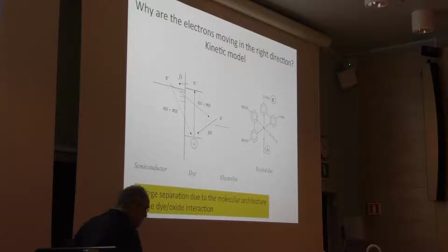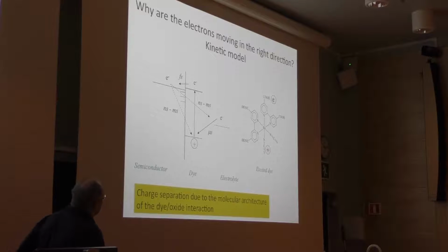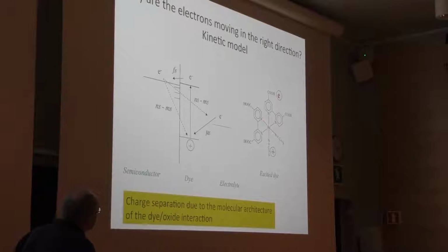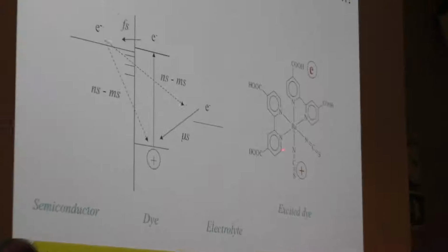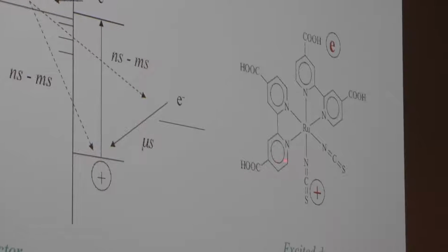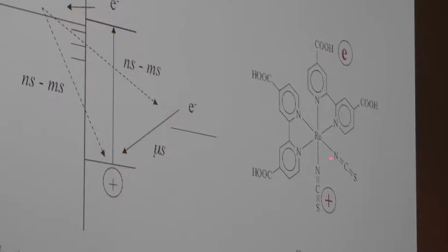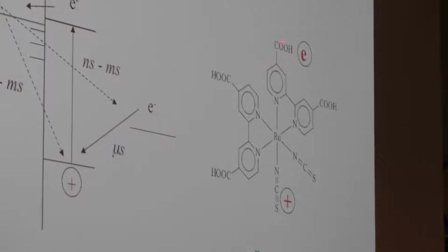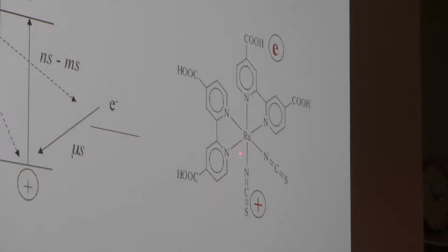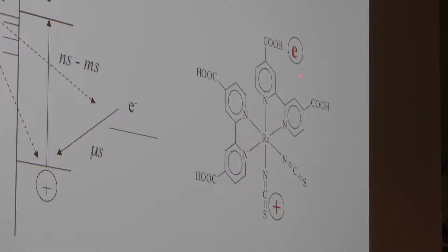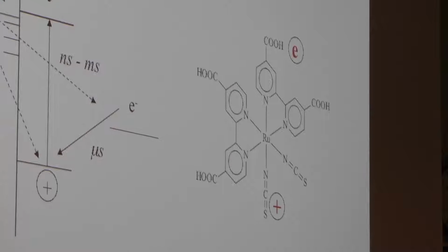So here was the explanation also for the charge separation. I said you had a built-in electric field for charge separation. We could explain then, after some years, that actually the dye architecture can separate the charge itself. So this is the famous N719 dye from Grätzel's group. It has these thiocyanate ligands and the carboxylated anchoring groups. And when we studied with synchrotron and quantum chemistry where we have the excited electron, we found it to be on the pi star orbital of the carboxylic groups. And that's very favorable because that anchors to the TiO2, so we have a fast injection.